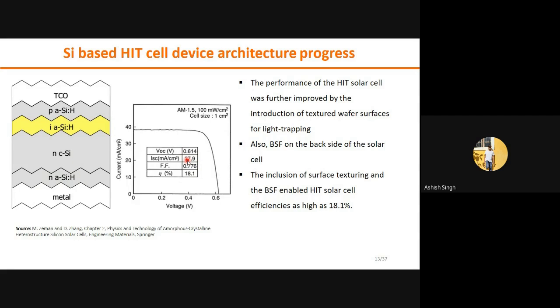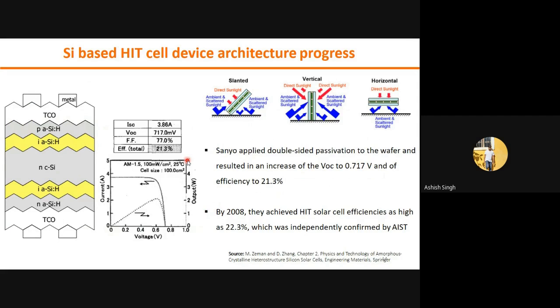Then after that, to improve further, they took the textured wafer and put the passivation layer on the front and both sides, so that most of the dangling bonds will be saturated by the passivation layer, and then they put P-type amorphous silicon on top and N-type amorphous silicon on the bottom, which will act as an electron tunneling layer, and P-type will be the hole transport layer.